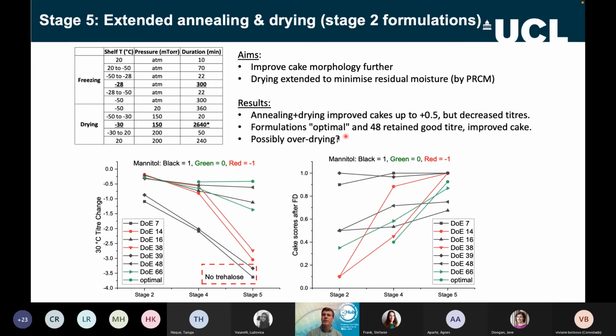Just to note, there was other literature out there, I think from GSK, that looked at these kinds of issues, and they found that if you dry it too much, you can also lose titer. So viral vectors don't like to be very dry, but the problem is if you don't dry it enough, your cake will collapse back and melt when you warm it up again to room temperature. So it's a real art to getting the right amount of drying.